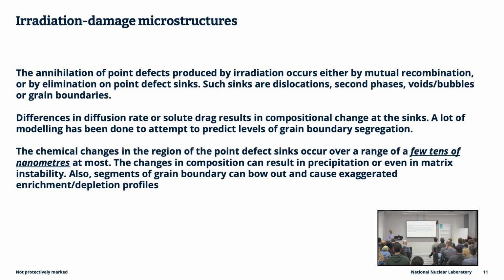So, well, I've already kind of spoiled some of this slide. Why are we doing this? We're doing it because of the damaged microstructures, I mean, Jack illustrated what those look like, but in irradiated materials, the defect flows that produce those structural defects also produce chemical changes over the distance, typically only of a few nanometers, although at higher temperatures, those diffusion fields are somewhat larger.